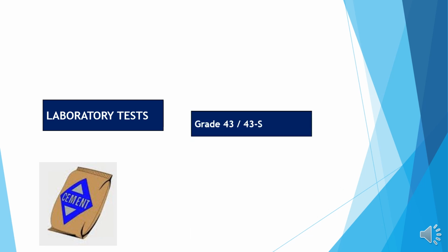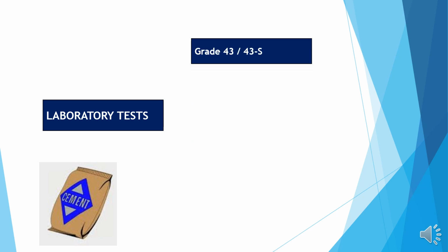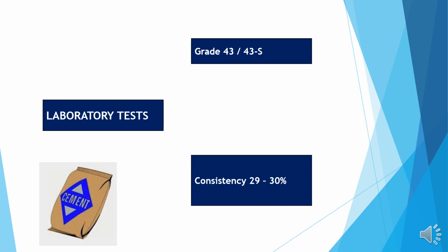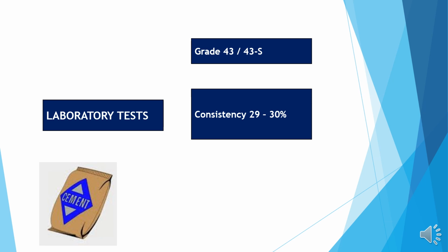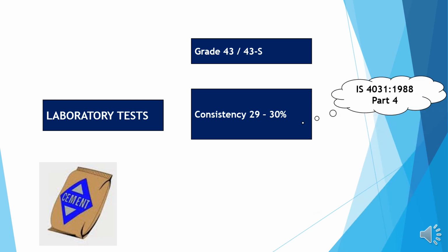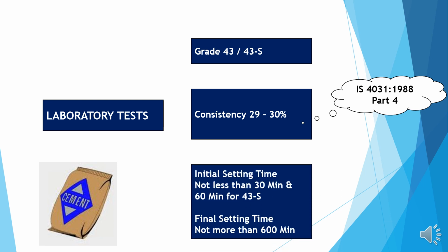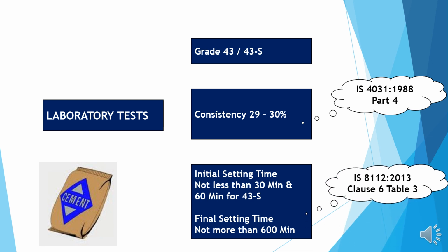Cement laboratory test. Grade 43S. Consistency 29 to 30%. Refer IS 4031 Part 4. Initial setting time not less than 30 minutes, and 60 minutes for 43S. Final setting time not more than 600 minutes. Refer IS 8112 Clause 6 Table 3.